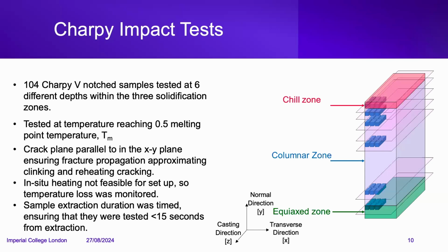Another thing to note is that because in situ heating was not feasible, a temperature loss study was conducted for each of the target temperatures to ascertain how fast the temperature loss rates were and ensure that the tests weren't too far away from the target range.